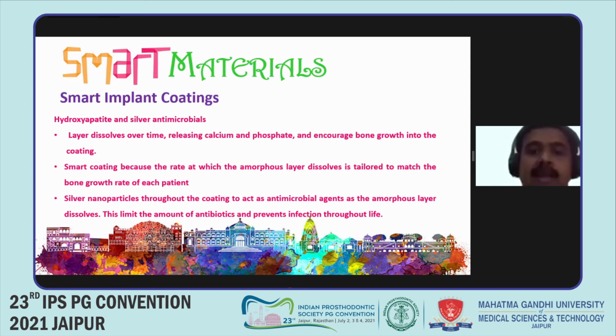It releases the calcium and the phosphate and encourages the bone growth into the coating. Smart coating, because the rate at which the amorphous layer dissolves is tailored to match the bone growth rate in each particular patient.